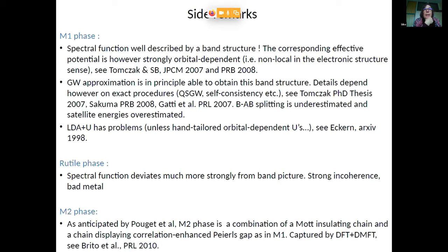However, the hybrid functional does something relatively similar, I think, to what either GW is doing or what also the effective potential that we constructed here in this 2008 paper, or 2007 Journal of Physics Condensed Matter, I think, where we're constructing a static potential, which is essentially reproducing the spectral function. So that tells you that you can find an orbital dependent, that means non-local, effective potential to actually get the band structure. You will not get the lifetimes, you may not get the temperature dependence of the more complicated phases, but you will get essentially a very nice picture of where the states are lying in the M1 phase.